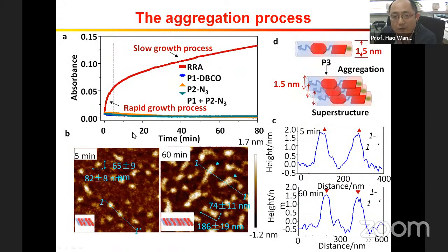For these two to meet each other, we also ran a UV experiment, because when they meet, the solution becomes turbid as they form aggregates. If you see this curve, in less than 10 minutes, a couple of minutes, the aggregation happens very quickly. So the system is very efficient.